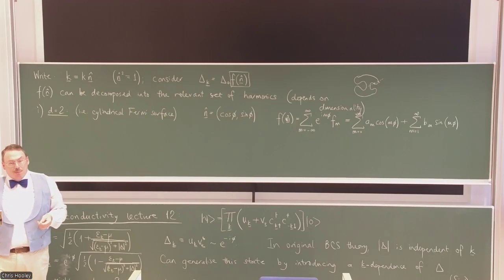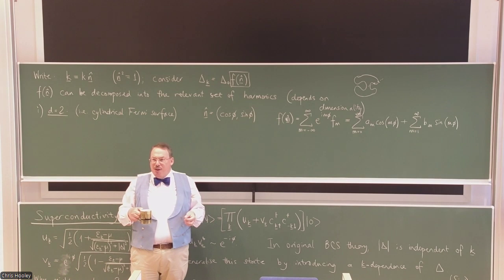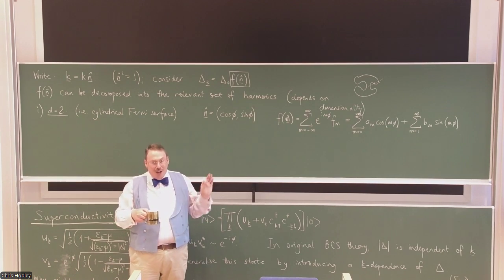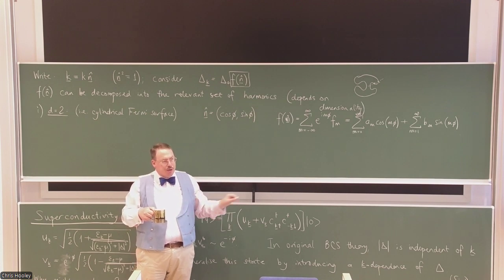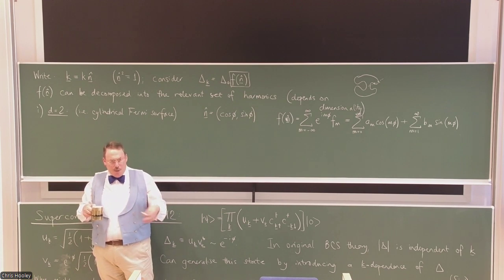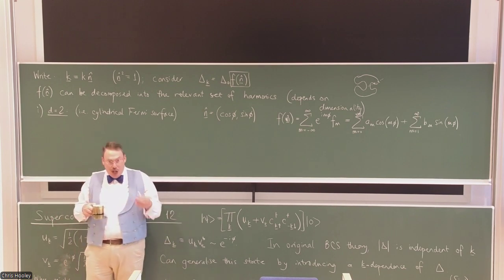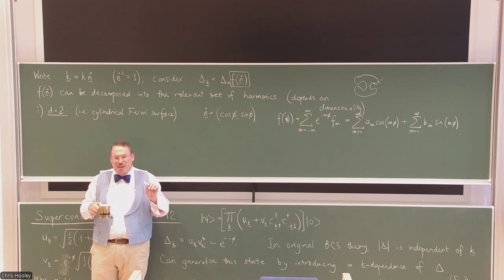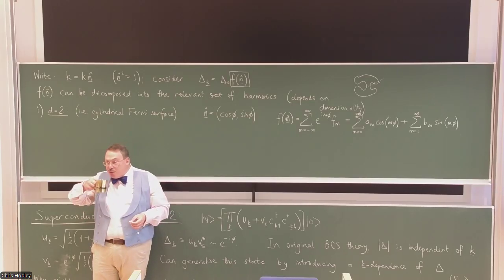And that's also an important point. People refer to superconductors like the cuprates as D-wave. They do not have the pure m equals 2 shape of the gap. If you actually measure what the order parameter is doing around the Fermi surface, and we'll discuss later how you do that, you find that higher harmonics are also mixed in. So it's correct to say that the cuprates are dominantly D-wave. They have the nodes, they have the zeros of delta in the place where D-wave would have them, but actually they don't just behave like a cosine in between those zeros.